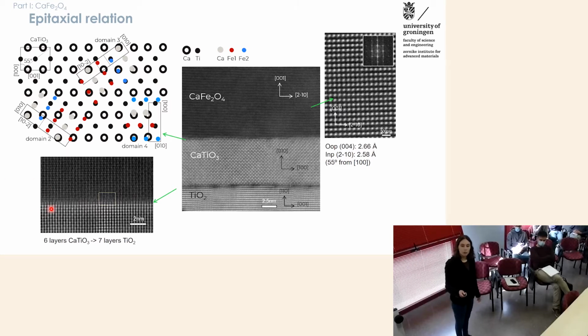But then, if we look at the interface between calcium titanate and calcium ferrite, we can make a sketch of how this surface will look. So in black, you can see here the atoms belonging to calcium titanate, and colored the cations of calcium ferrite. And there is a pretty good matching of these atoms with an in-plane orientation corresponding to domain type 1, but also when we rotate this by 55 degrees, which would correspond with the diagonal of the in-plane of the calcium titanate. So what's happening is that calcium ferrite is growing, forming islands which match the epitaxial relationship with the calcium titanate. And here, for example, in the TEM, we can see the calcium ferrite crystal layer at 55 degrees from the in-plane orientation of the calcium titanate.